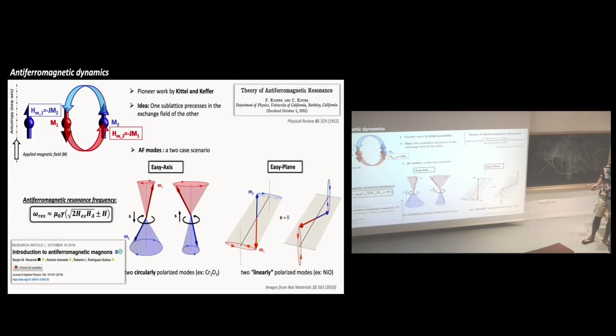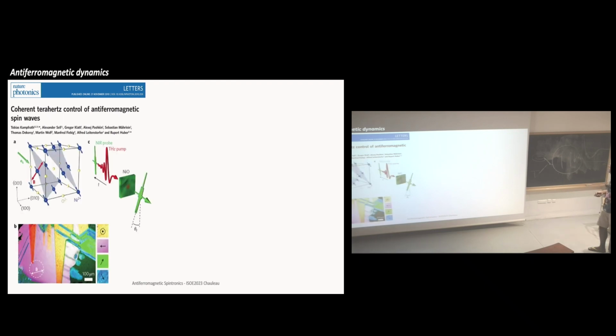Okay, so to illustrate this dynamics, there are some very nice recent measurements, and this one has been done in the group of Huber. I think it was 2010, and even if it's not so easy to measure, what they have done here, they have taken NiO, and to trigger dynamics, they do that with a magnetic field. Even if the magnetic field is not very efficient, they do that with a terahertz pulse of magnetic field, and they will probe it. Since it's a bulk crystal, they can't use magneto-optical effect, but they will probe it with a near-infrared probe.